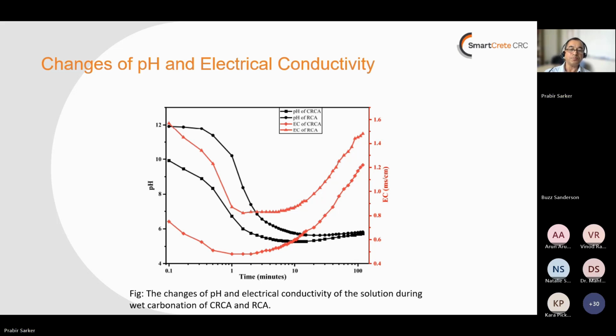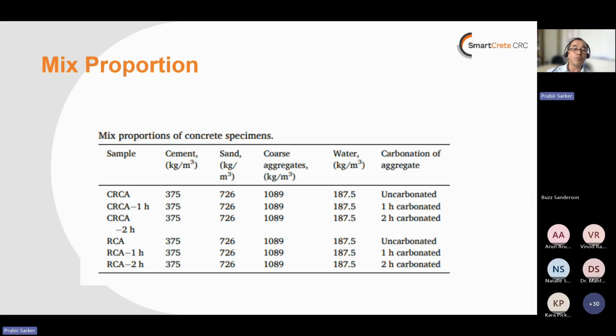So we can see with the increased duration of the carbonation, electrical conductivity increased and the pH decreased, because the calcium hydroxide has reacted to form calcite. So the pH has decreased. So this is a mix proportion using carbonated recycled aggregates for 1 hour carbonation and 2 hour carbonation, for CRCA and for recycled aggregate from the crushed cylinder concrete. Okay.